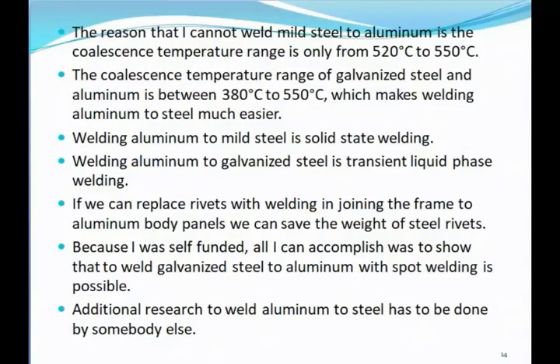The reason that I cannot weld mild steel to aluminum is that the coalescence temperature range is only from 520 degrees Celsius to 550 degrees Celsius. The coalescence temperature range of galvanized steel and aluminum is between 380 degrees Celsius to 550 degrees Celsius, which makes welding aluminum to steel much easier. Welding aluminum to mild steel is solid-state welding. Welding aluminum to galvanized steel is transient liquid phase welding.